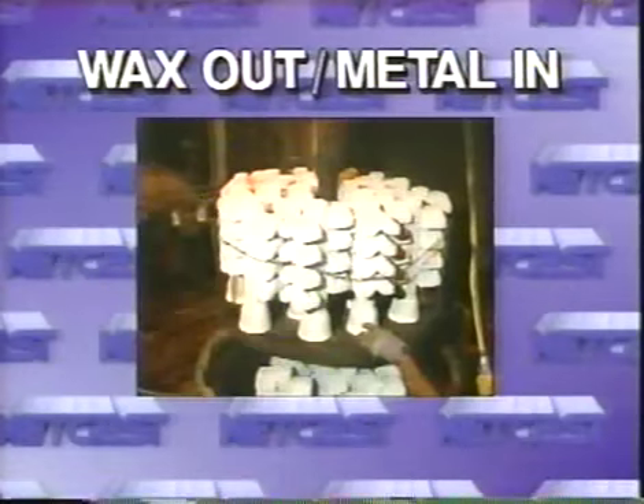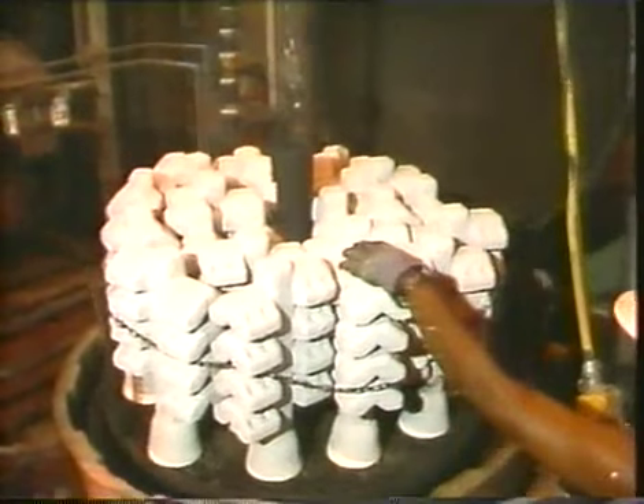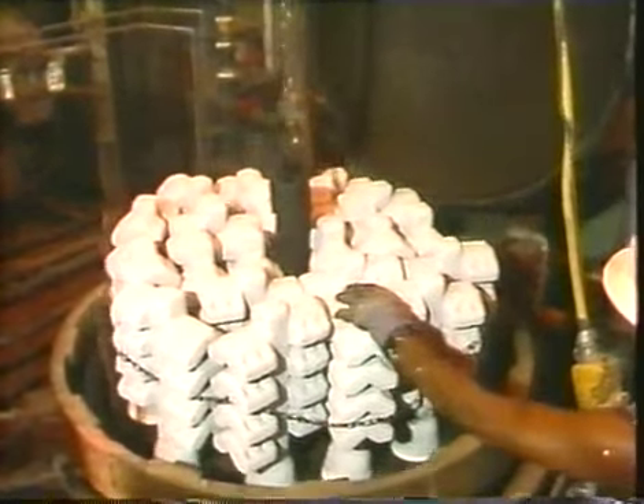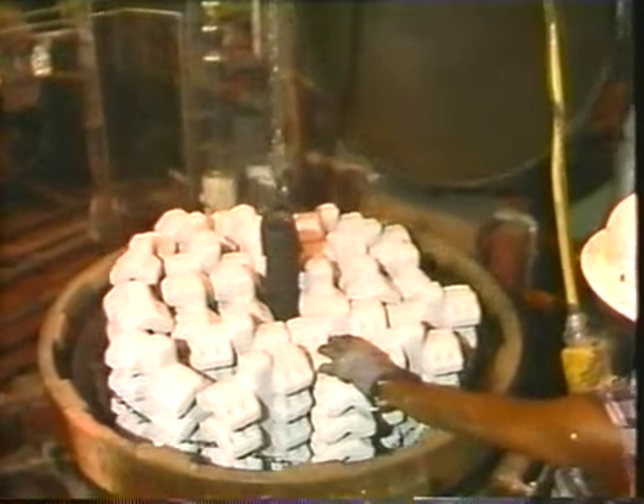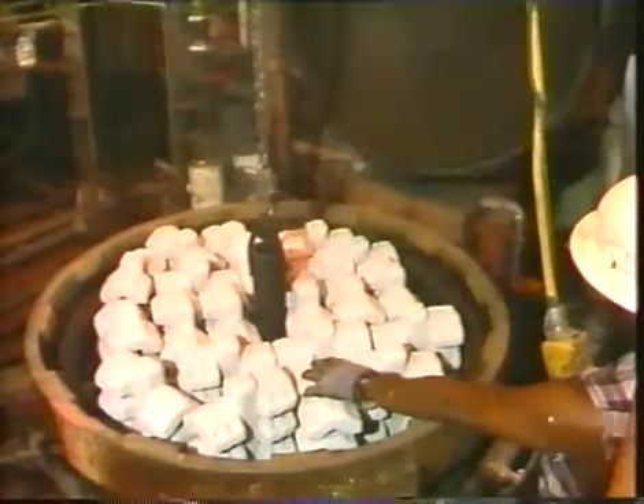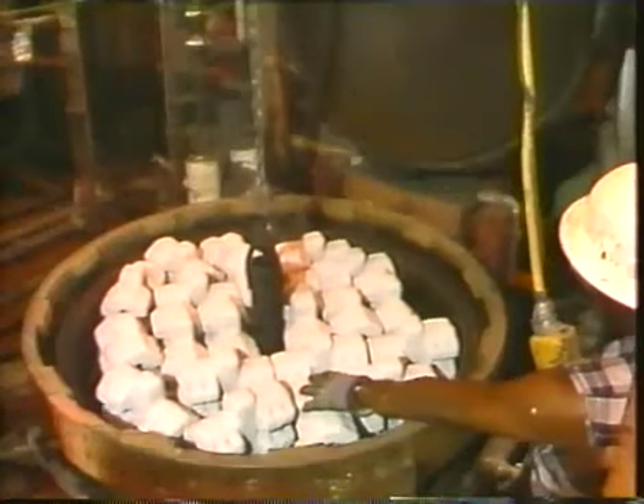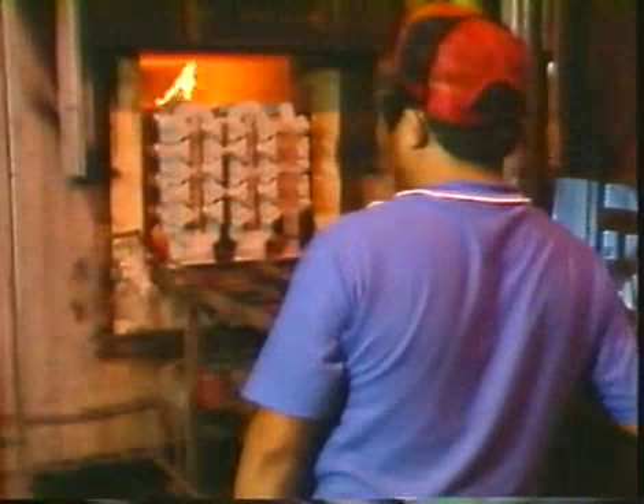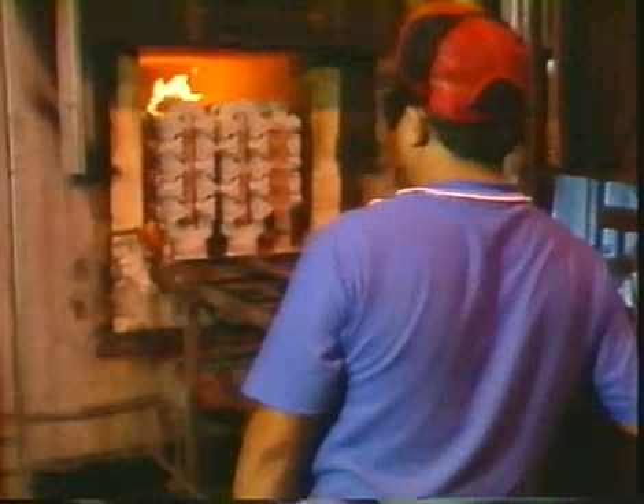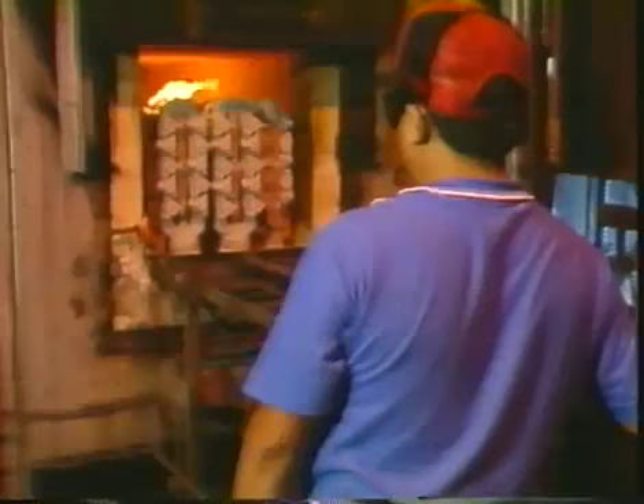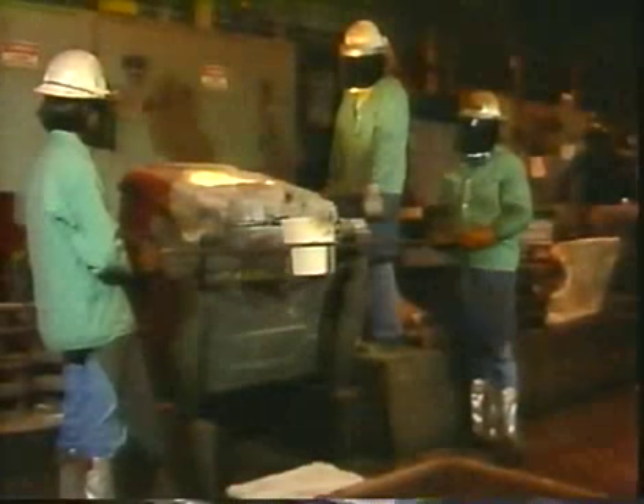The next step in the casting process is to remove the wax and fill the mold with hot metal. The removal of the wax is usually a two-step process. First, the major portion of the wax is removed in a steam autoclave. Next, the shell is placed into an oven where the last remaining wax is burned out and the ceramic shell fired. The metal, which has been melted in an induction furnace, is poured into a transfer ladle. It is then poured into the preheated shells and allowed to cool.